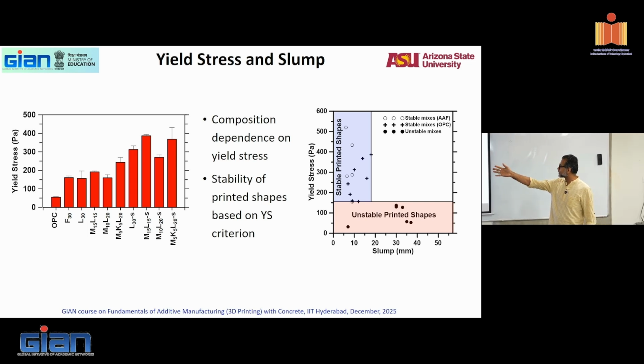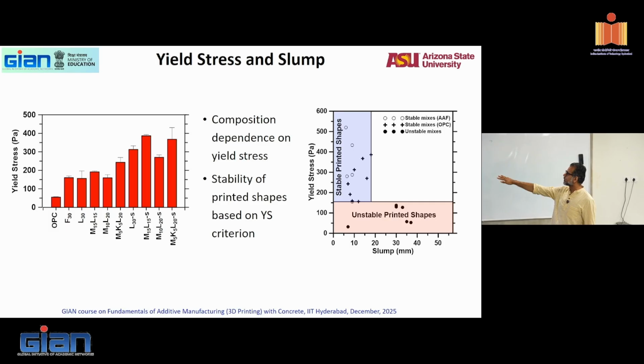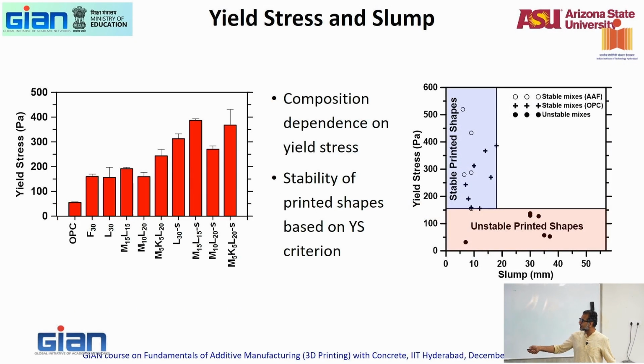So for different materials, if you look at yield stress as you add more and more materials, again, many of the concepts we talked about, you can see here, right? If I add 30% of limestone and replace cement with that, and limestone is much finer than cement, see my yield stress increases, right? Why? The number of particle contacts have gone up. As I go with smaller and smaller sizes, the number of particle contacts have gone up, yield stress has gone up. Similarly, everything on the right side of OPC here are systems where cement has been replaced with particles of smaller sizes, right? And then with metakaolin, you'll see the yield stress really, really going up.